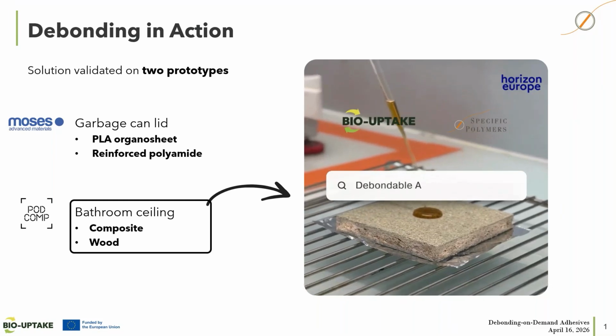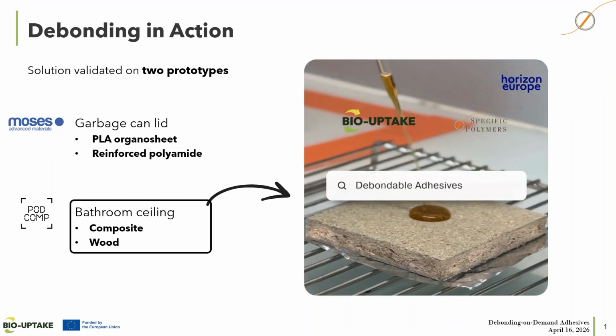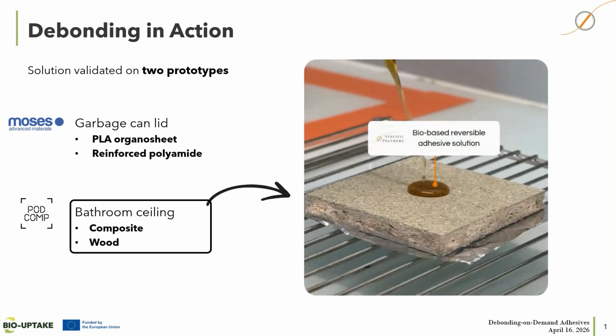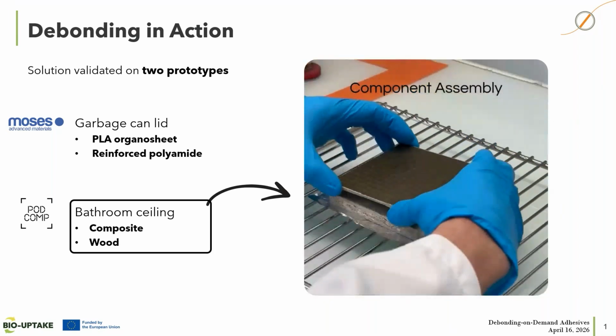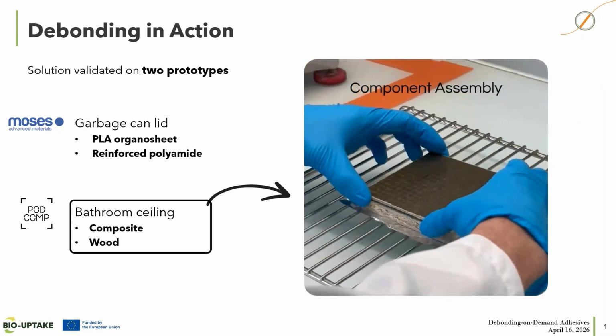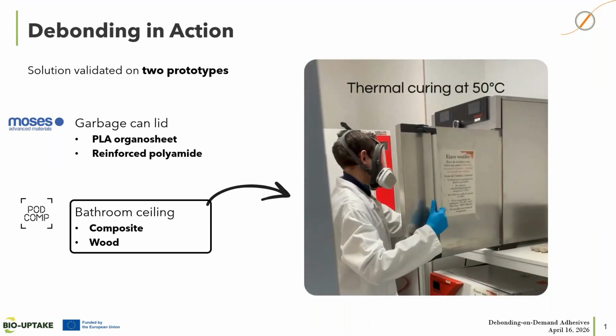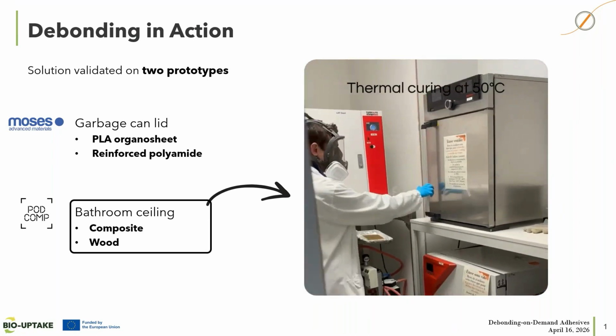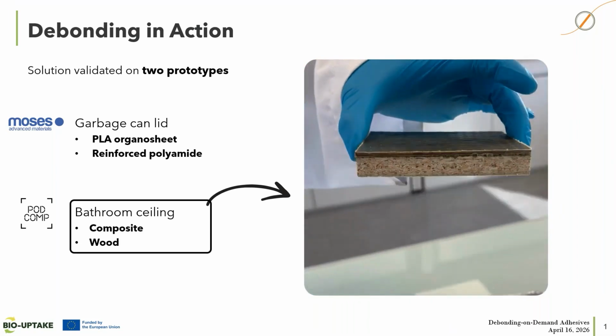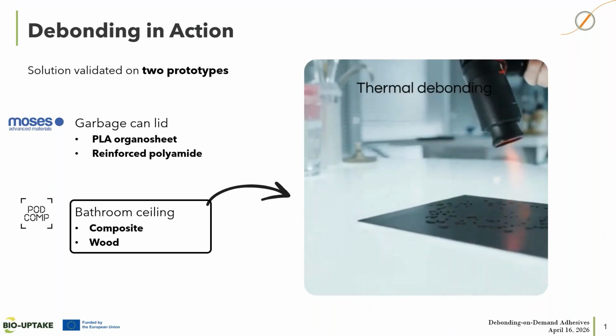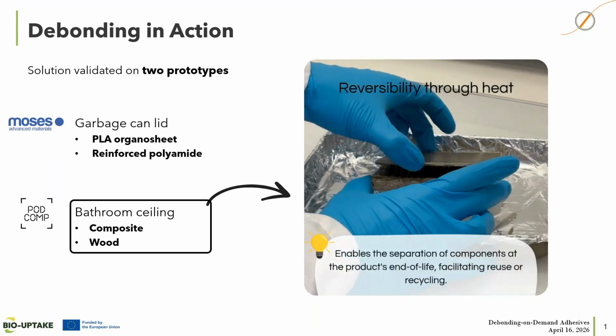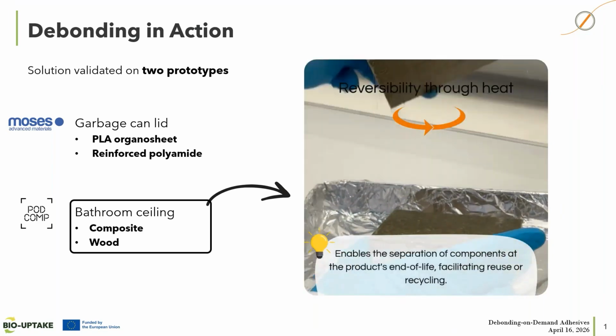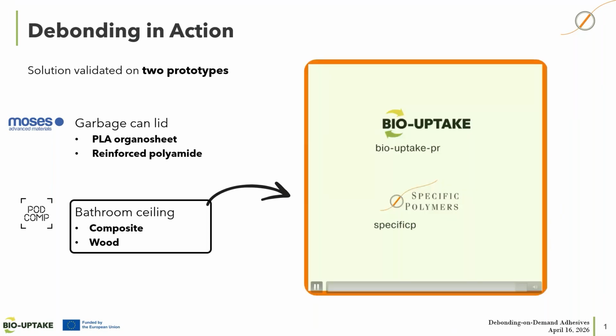So we begin by applying the adhesive onto one of the substrates, and the second component is then assembled to ensure proper contact between both surfaces. Then the system undergoes thermal curing, and at this stage, the components are strongly bonded and ready for use. And when separation is required, heat is applied, triggering the reversible chemistry. And the adhesive loses its strength, allowing easy disassembly of the substrate, as shown during this video.